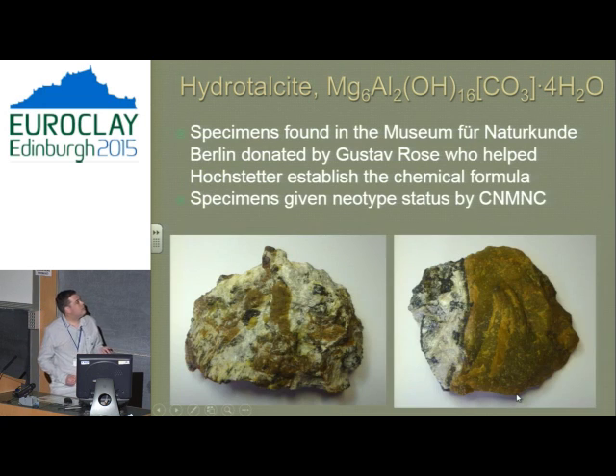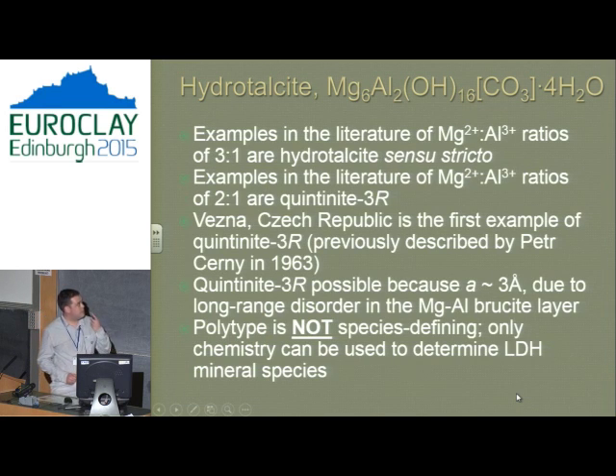So in looking at these specimens, we did X-ray diffraction, and these are actually the 3R polytype. So that's okay. We then looked at the chemistry of them, and these were okay too, 3-1. So the type locality with the old specimens is fine. So hydrotalcite does exist. But the examples in the literature where there are 2-1 is quintinite and not hydrotalcite, which is a completely different mineral with a different space group, has different properties, and it shouldn't be confused.